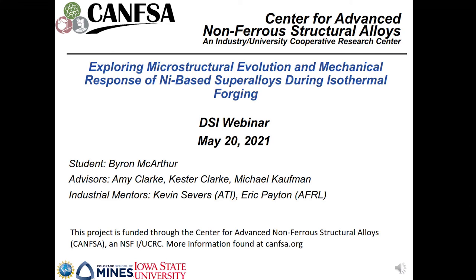So at that point, the primary gamma prime pins all of the gamma boundaries. After that isothermal forging, you cool, and that reprecipitates the secondary gamma prime. And then you reheat to get to the final microstructure that you're trying to achieve. During that reheat is when, depending on the prior processing, abnormal grain growth can occur. In that reheating, you're dissolving those reprecipitated secondary gamma prime as well as the primary gamma primes that you still had from the isothermal forging.